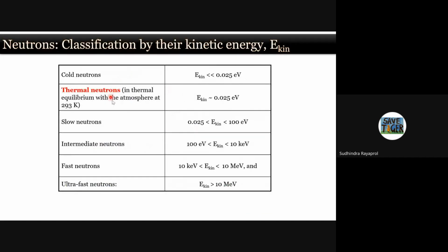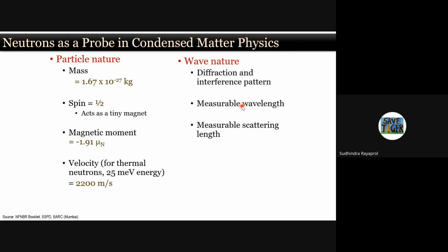So if you look at the properties of thermal neutrons, from a reactor source you get plenty of neutrons with different energy levels. You can have slow neutrons, intermediate neutrons, fast neutrons, and so on. But what we are interested in for diffraction purposes is the thermal neutrons, which have a kinetic energy of about 25 meV at room temperature, and in terms of wavelength, it is comparable to the wavelength which we see for interatomic distances, about 1 angstrom or so.